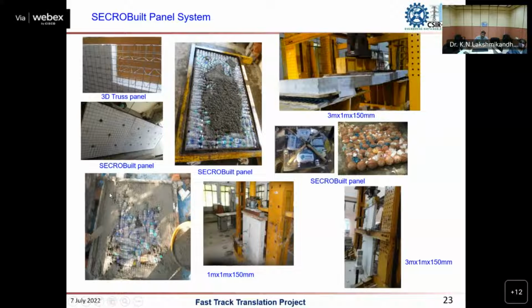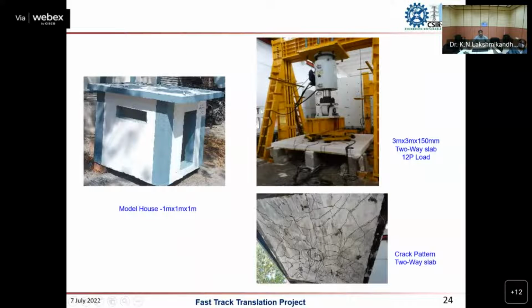So before going to the market, we tested all the aspects, in flexure as well as axial compression, and we also tested the behavior of the panel at 1 meter by 1 meter, and a large panel of 1 meter by 3 meter size. We kept the thickness at 150 mm, which includes 25 mm skin at both ends and 100 mm thickness of infill.